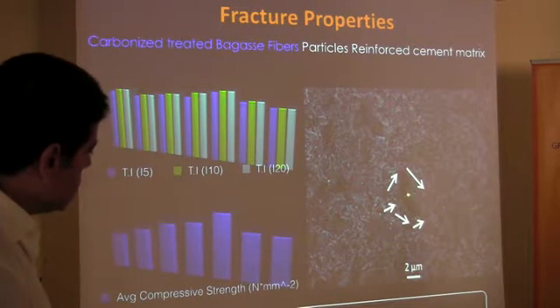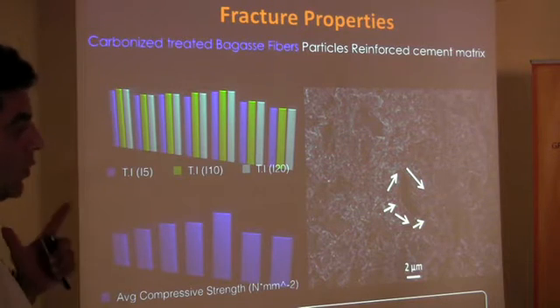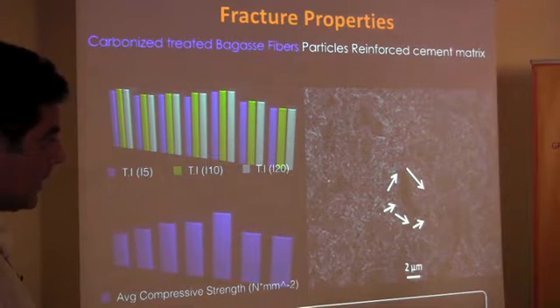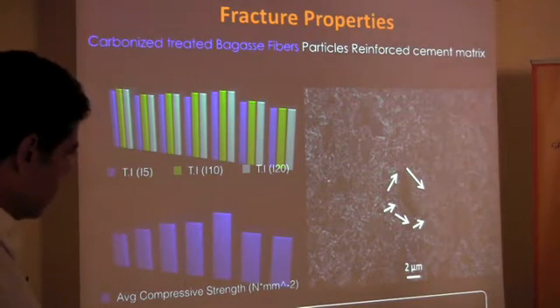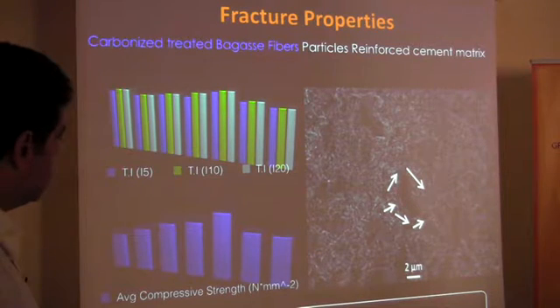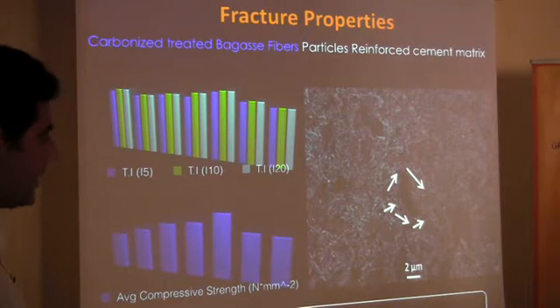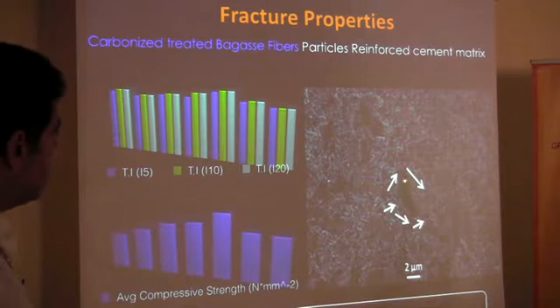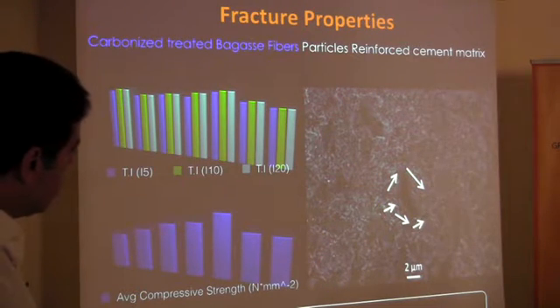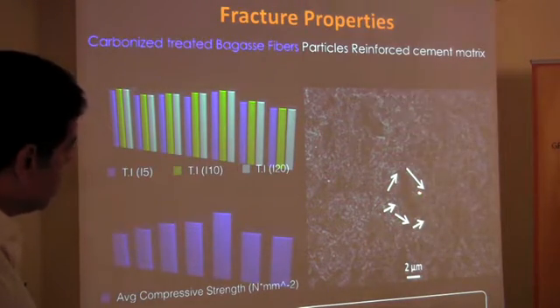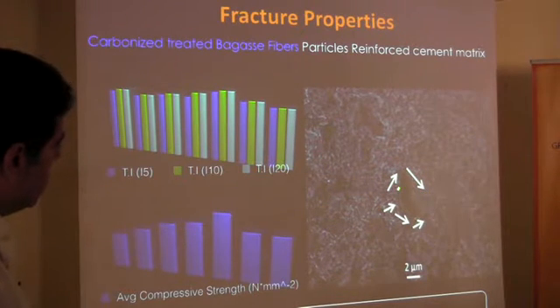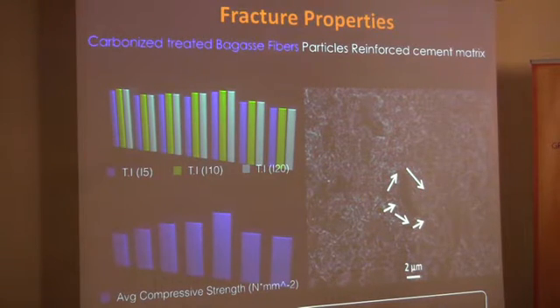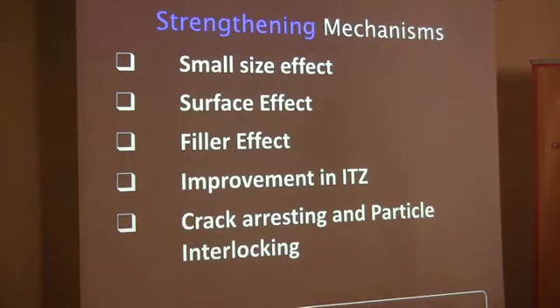You can see this is carbonaceous inerts that normally, with respect to silica fume, did not react with the matrix. It remains as inerts, and the crack has to circumnavigate the inerts, so it increases a lot the quantity of fractal surface. The strength mechanisms, of course, are many.